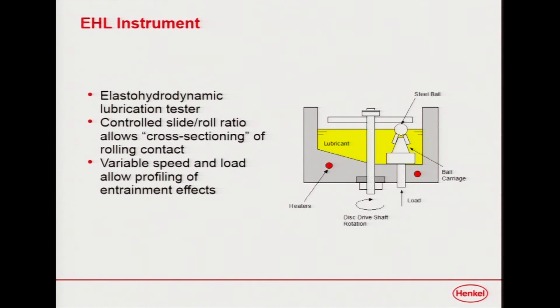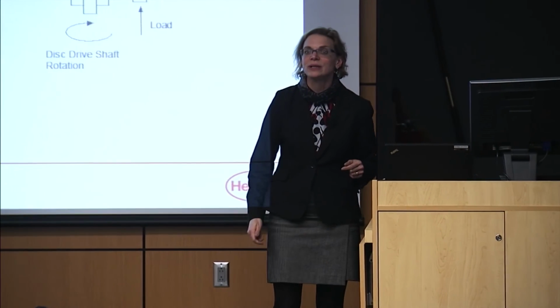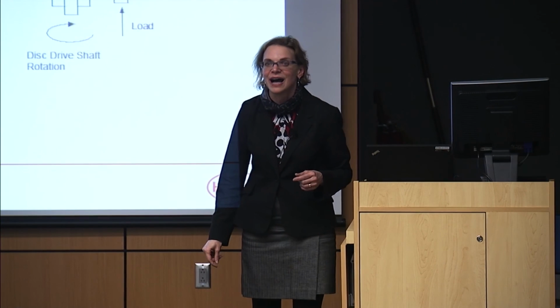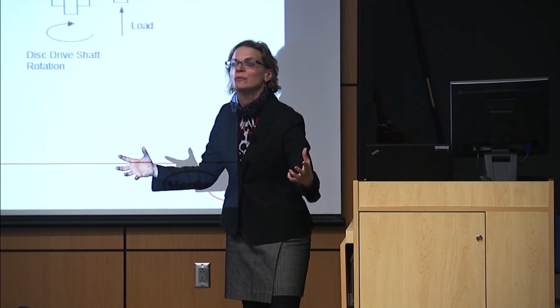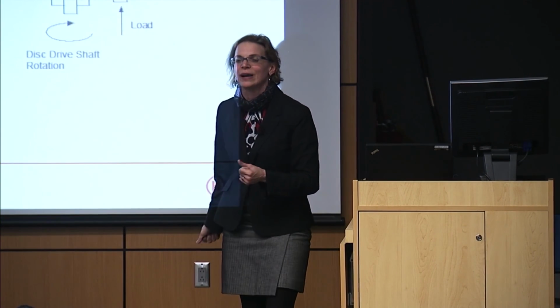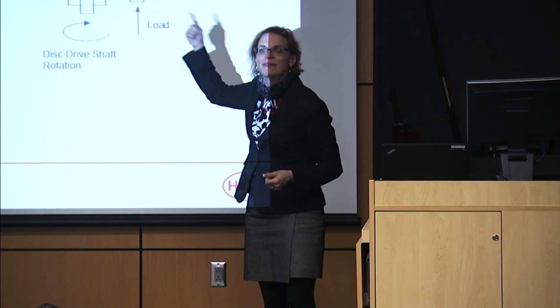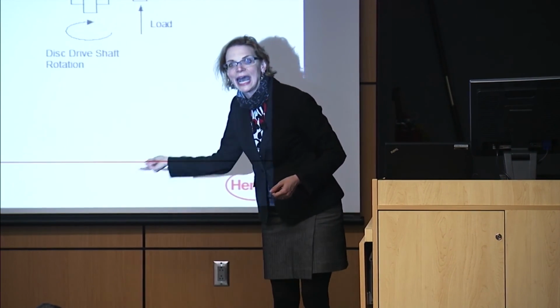So we found a device that was developed actually by our friend from England, Dr. Cameron, called the elastohydrodynamic lubrication tester. And it's a point contact, which is not like our steel rolling mill. But what's very interesting about it is you can vary the speed of the steel ball and vary the speed of the flat plate that it's rotating against. And by doing that, we can introduce sliding into the contact. So we can't really create a rolling mill because that would be very expensive in the laboratory. But we can actually control the amount of slide and rolling that's occurring in the contact with this thing.